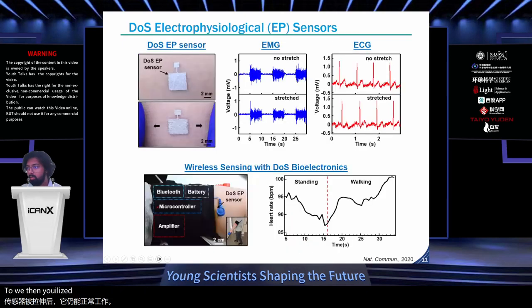We then utilized our conductive ink for electrophysiological, or EP, sensors. Here you can see that the DOS EP sensors show good signal quality, even when stretched, and easily capture both ECG and EMG. One relevant clinical application is for stress tests. These are typically done in the hospital, used to evaluate heart condition. We developed a Bluetooth-based data transmission circuit with some off-the-shelf components to interface with our drawn-on-skin sensors. And you can clearly see here that as the subject rests, the heart rate decreases, whereas when you walk, the heart rate increases.